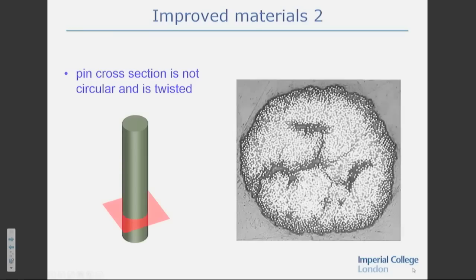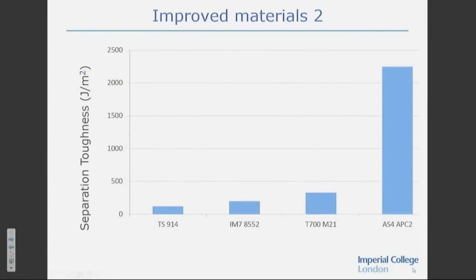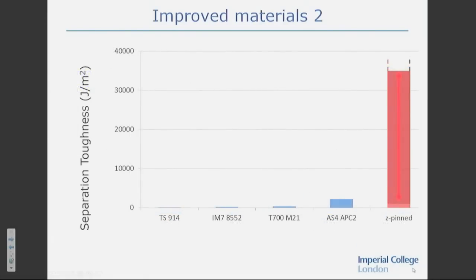Energy absorption mechanisms. And how do they fit on this plot here? Well, it turns out Z-pinning can hugely change the separation toughness. And we're talking about ranging from a few thousand up to tens of thousands. And it simply depends on the length of the pin, so the pull-out length, and how many pins you put in a given area. So we've got ways of improving the toughness of the material.